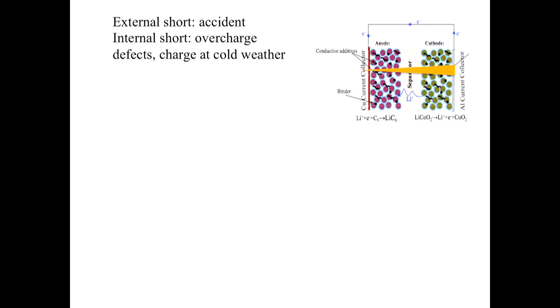Something is happening called shorting. It can be an external short, when you have an accident and something bumps onto the battery. You can also have an internal short, due to not controlling your charging right. You overcharge, you build lithium dendrite that shoots out from anode to cathode. Or there's a defect, a metallic particle embedded inside during manufacturing. That can easily cause shorting and induce dendrite growth.